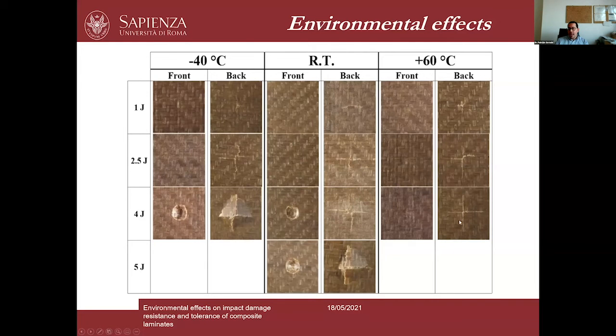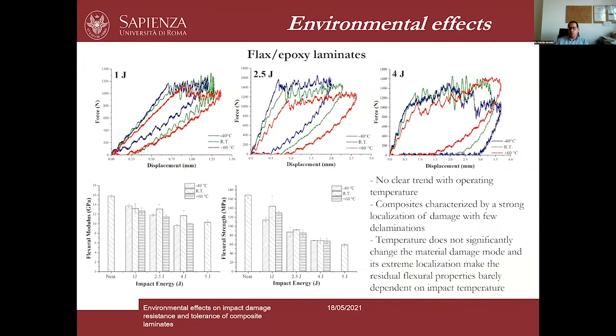And it is these micro cracks that actually govern the final failure of the composite, because once impacted, we also performed 4-point bending tests after impact, just to assess the damage tolerance of these composite materials. Here you can see the results in terms of the flexural modulus and the flexural strength as a function of the impact energy. Of course, there is a decrease in these properties with an increase in impact energy, and this is pretty standard. The problem is that we didn't detect any clear trend with the operating temperature.